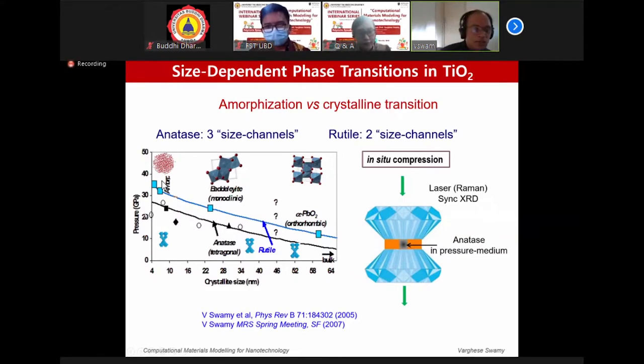And what you see here is a metastable phase diagram to the left, where pressure versus crystallite size of anatase is shown. So these are experimental results. What you see on the x-axis is the crystallite size, the average crystallite size of your sample, starting with 4 nanometers up to 64 and beyond. And the vertical axis is the pressure. So when you start off with anatase of, let's say, 6 nanometers here, when you compress the material in a diamond anvil cell, it stays metastably up to about 30 gigapascals instead of transforming to the phases I discussed earlier.